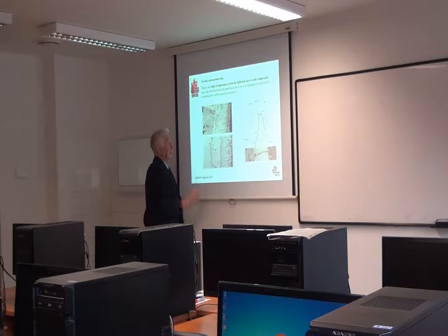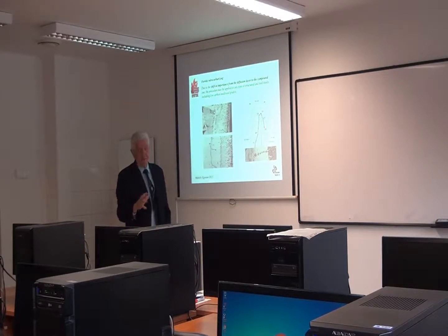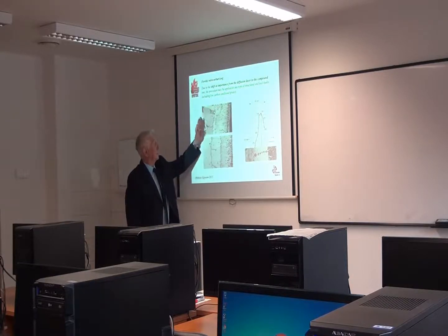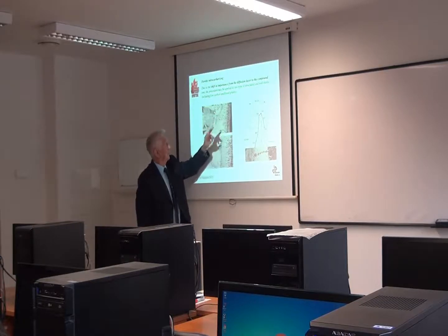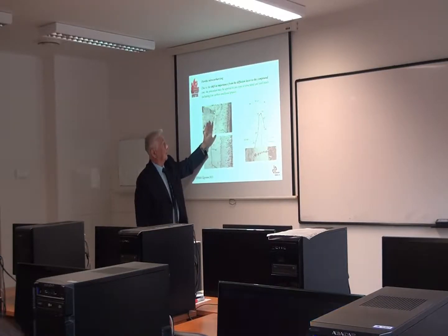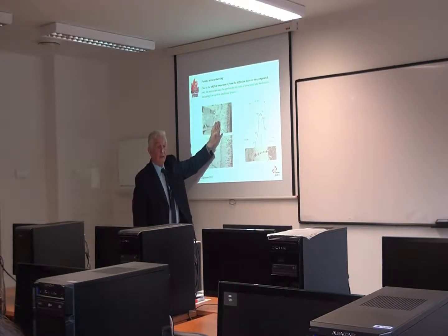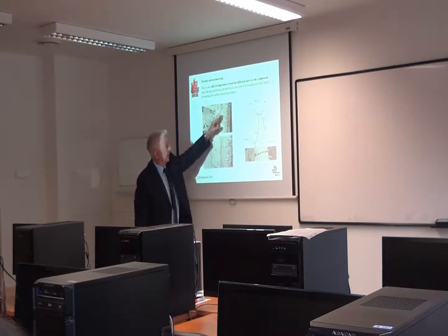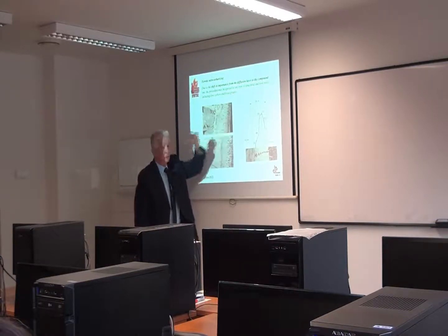This is at high magnification. It's about 1,000 times the microscopic magnification. And you see this is the substrate. Well, we have the diffusion and some nitride precipitates you can see here. But then you have the combination layer, the compound layer, which is practically that layer with a kind of ceramic character. And then the outer layer with a porosity.